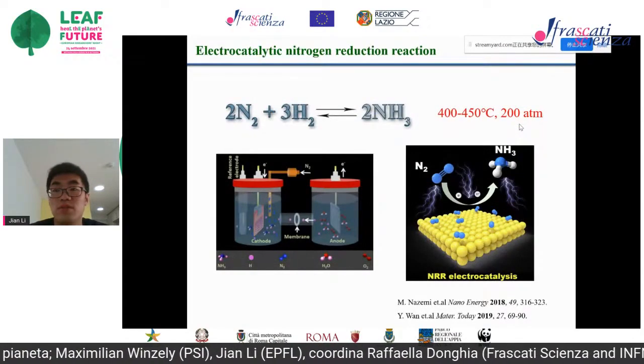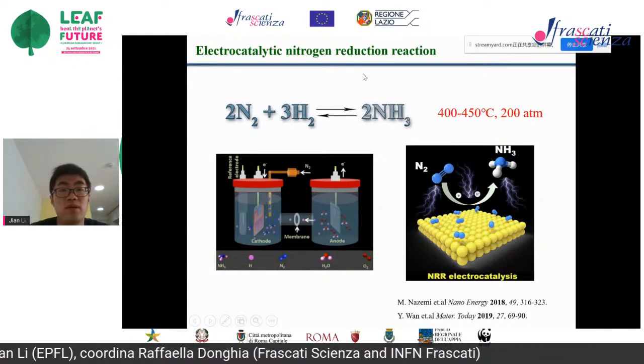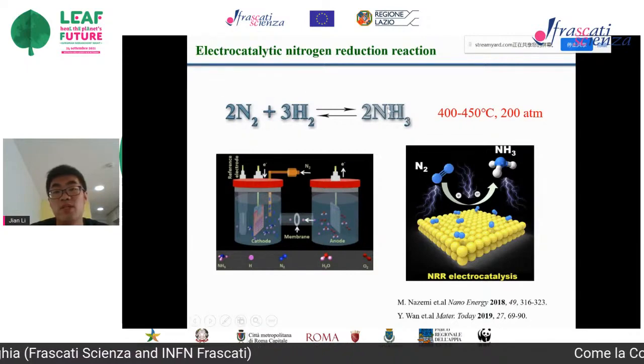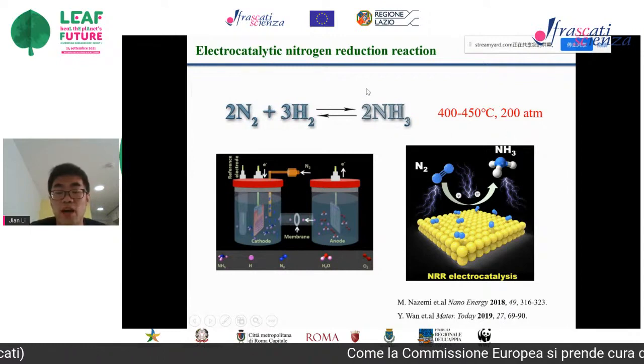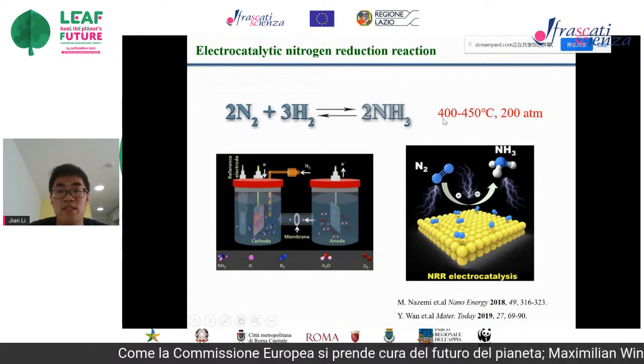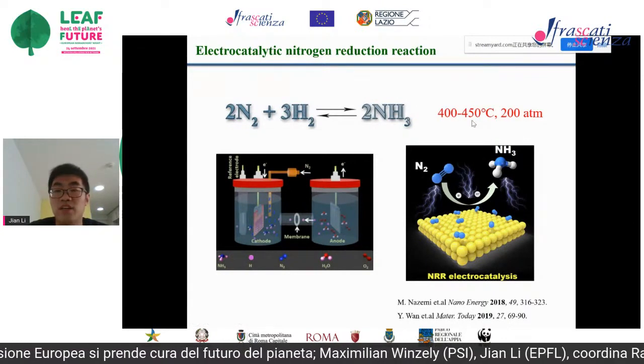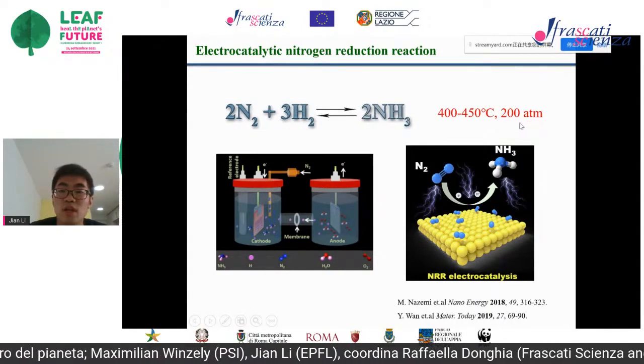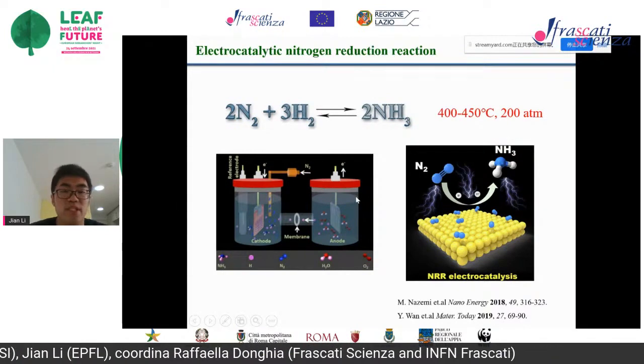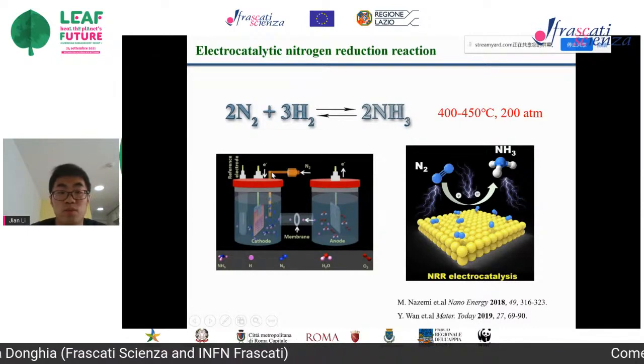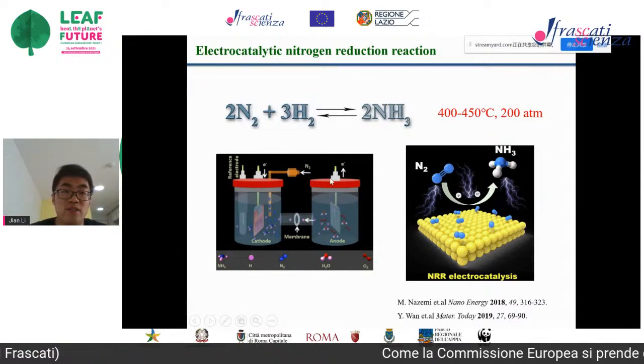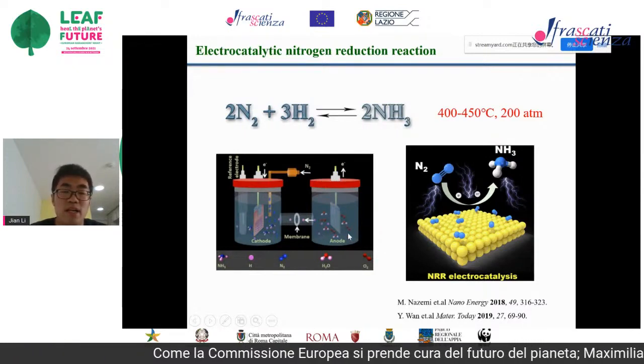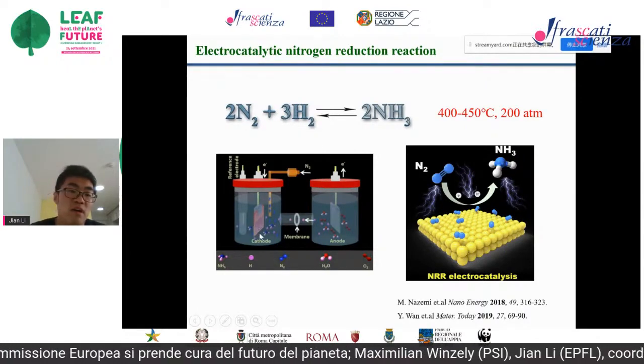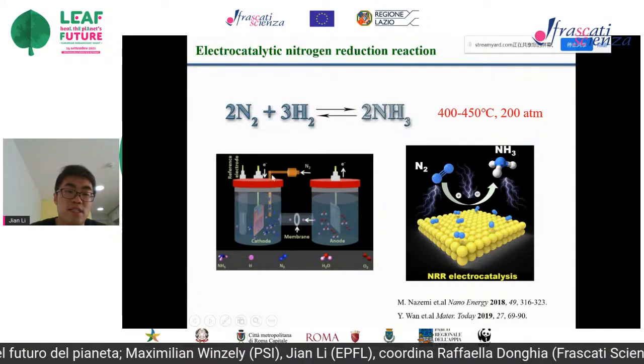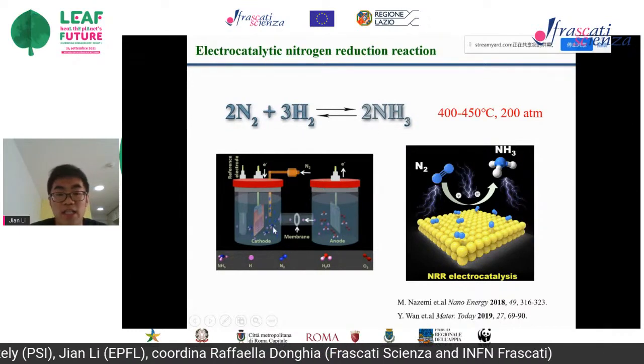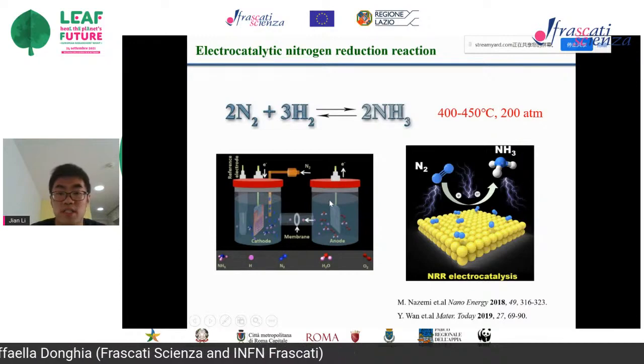And next, I will introduce some of my Marie Curie project. My Marie Curie project is focused on nitrogen reduction. As we know, in industry, ammonia is synthesized by the Haber process, but it proceeds under high temperature and high pressure. So if we can synthesize ammonia at room temperature and ambient pressure, it can save a lot of energy. So electrocatalytic nitrogen reduction provides a promising way. We can deposit our catalysts on this electrode, and then we degas nitrogen, and the nitrogen can be reduced to ammonia. And on this side, oxygen evolution occurs.